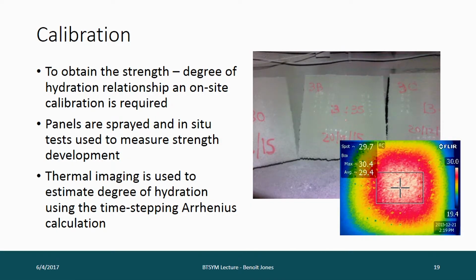So we can use a thermal imaging camera, get a temperature history, and calculate degree of hydration. But we need to relate that to strength. With in situ concrete, that's really easy. You just cast some cubes and crush them at different times. But with shotcrete, you can't really do that. You can't spray shotcrete into a cube mold. You can't mix it by hand fast enough in the lab, even with mortar, and then you get the wrong strength because it's not as compact as the actual shotcrete.